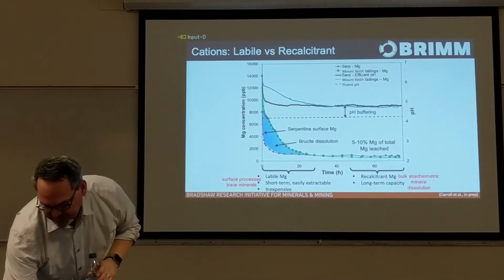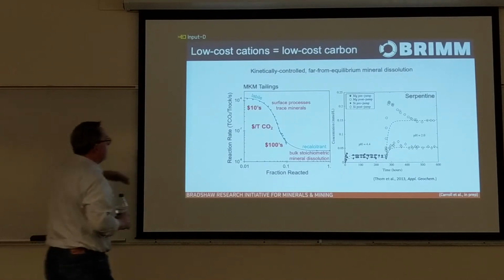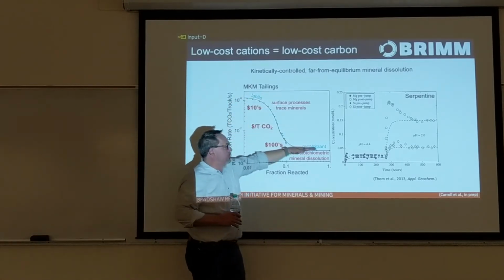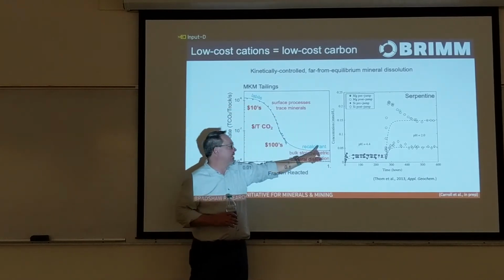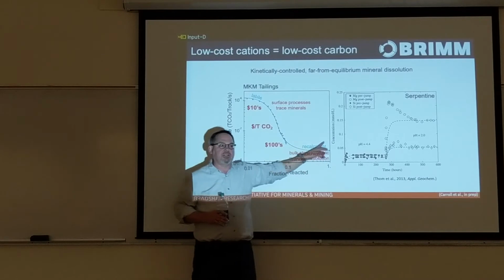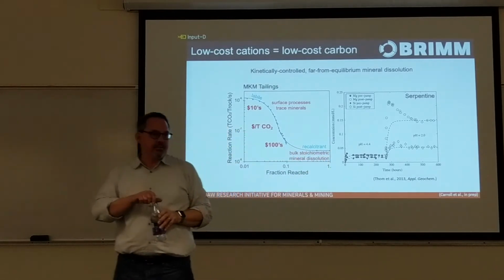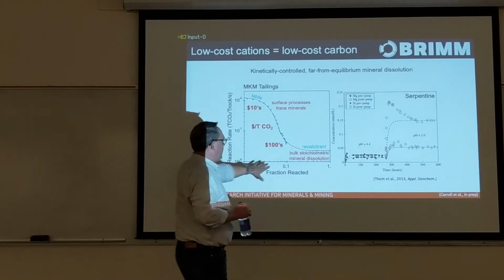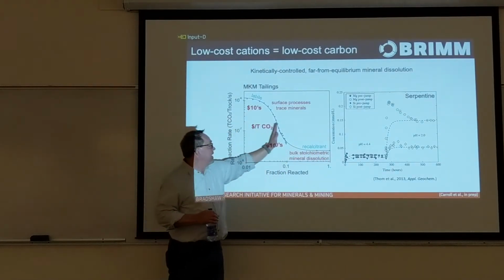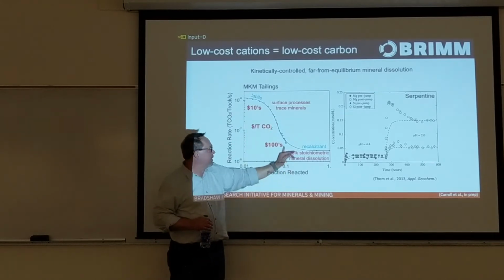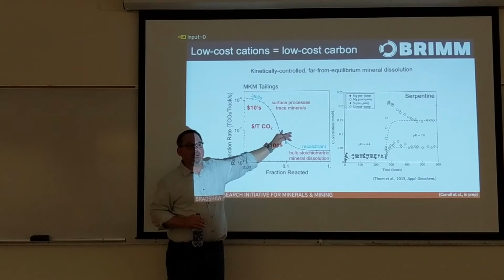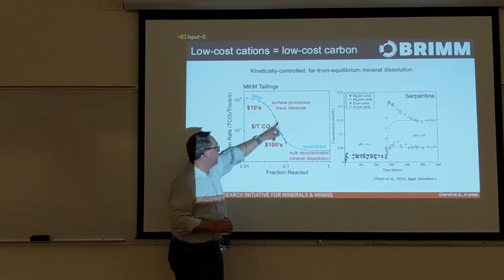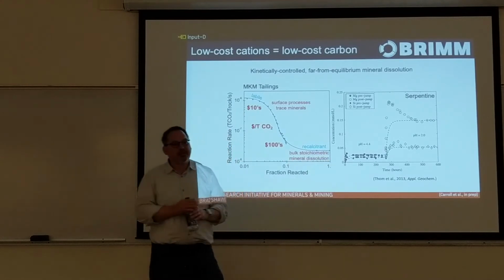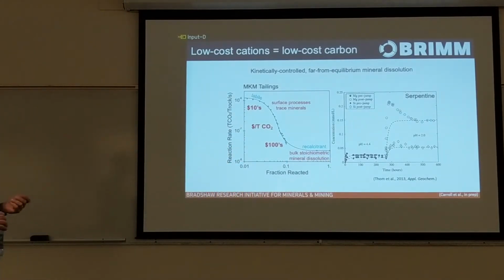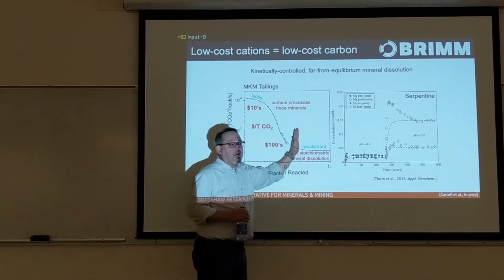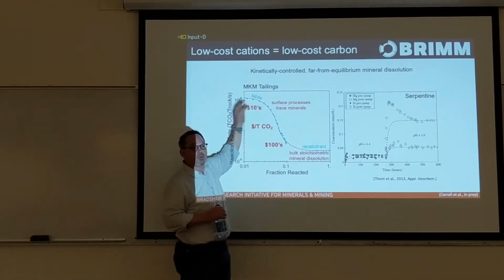So if we plot that in terms of CO2 equivalent reaction rate, this is the same experimental data. We essentially have a couple of orders of magnitude drop in reaction rate from the early period to the late period. These reaction rates are the textbook reaction rates that you get from mineral dissolution kinetics in a geochemistry textbook. This is far from equilibrium, bulk stoichiometric mineral dissolution. But what we find is that a significant fraction of the magnesium for this sample, about 8% of the total magnesium content of this sample, is extracted under this rapid regime before we tail off down to the slow regime. So a significant amount of the magnesium is actually extractable on this time frame of a day or two under these conditions. And so the key is understanding what controls that.